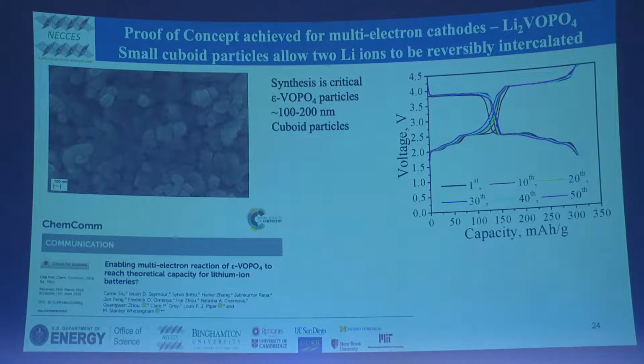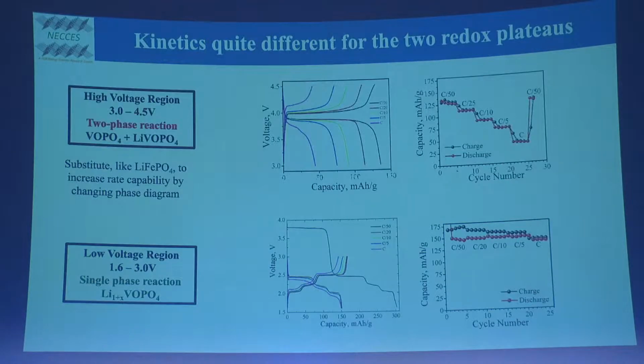The main point to notice here, the black curve here is the first cycle. The purple one is the 50th. The 50th cycle is in fact better than the first cycle. So there's less loss there. So this was really proof of concept it would work. Like everything else, we got proof of concept, it doesn't mean it's going to be viable commercially.